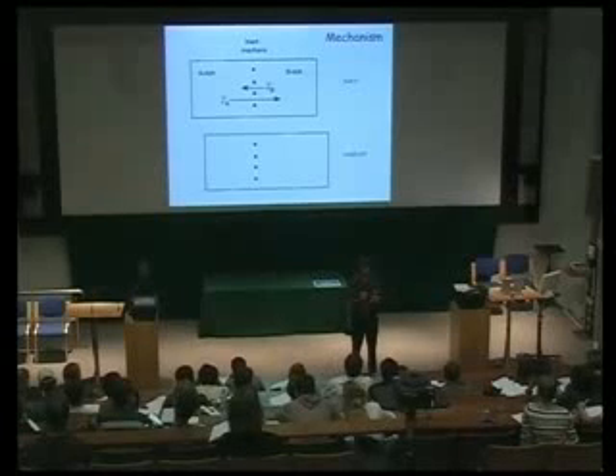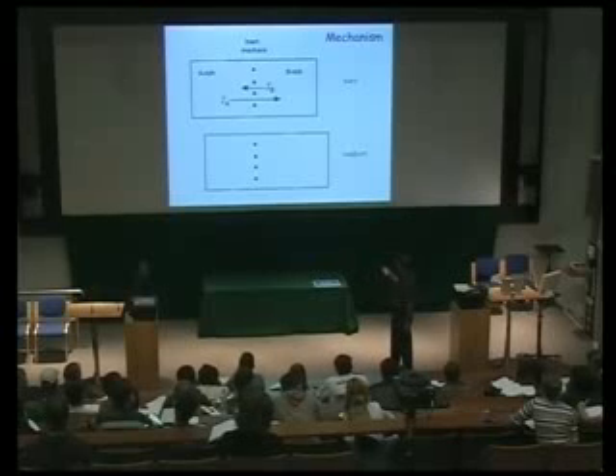But before he started the experiments, he put some inert markers. So this was actually a copper and a brass diffusion couple, and you put molybdenum wires in the middle and fixed them to the laboratory bench. So that's a unique position which doesn't change during the course of the experiment. Those are known as Kirkendall markers. Now, if you have a greater flux in this direction than in this direction, then the whole specimen should move in your laboratory frame, right? Laboratory frame is your molybdenum wires. And sure enough, the specimen was observed to translate as diffusion happened.